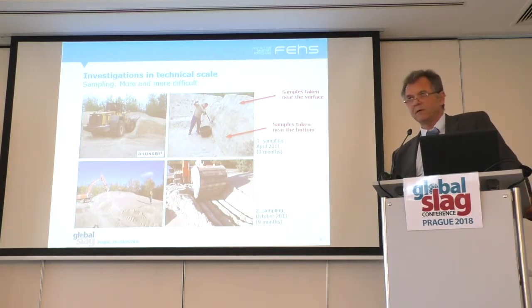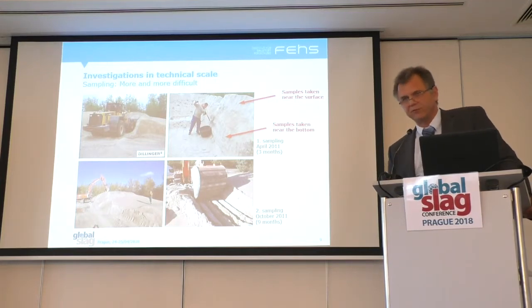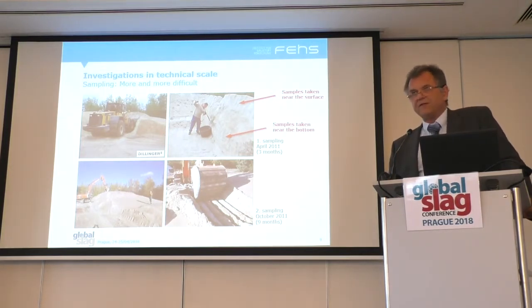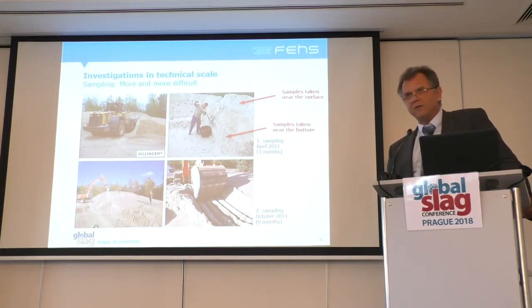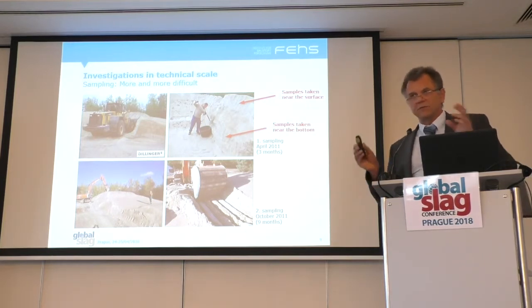Looking at PSD, chemistry and glass content, we found the same reactivity as we have today for a similar slag, regarding the not-the-best chemistry. And then afterwards they started indeed to use this old heap of GBS. Sometime later they stopped, because the hope to have really 1 million tons of pure GBS was not true. That was another story. But we found every time the same story. We did not find any decrease in strength outside of the statistical range.